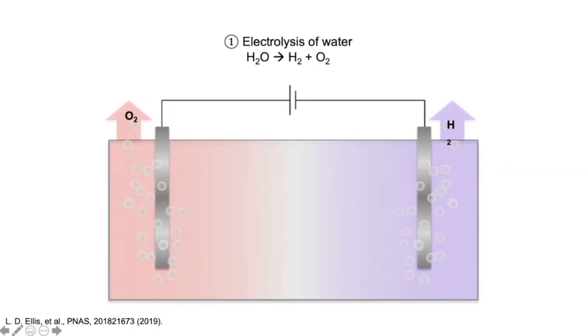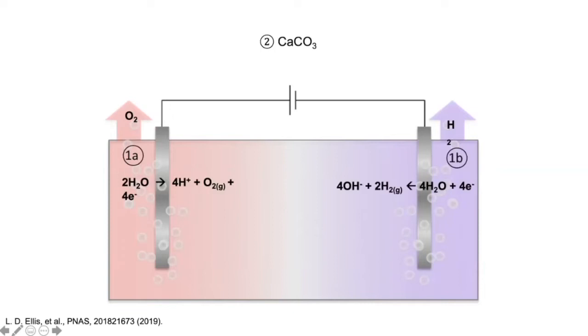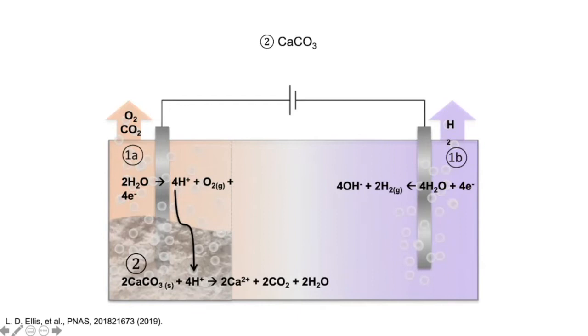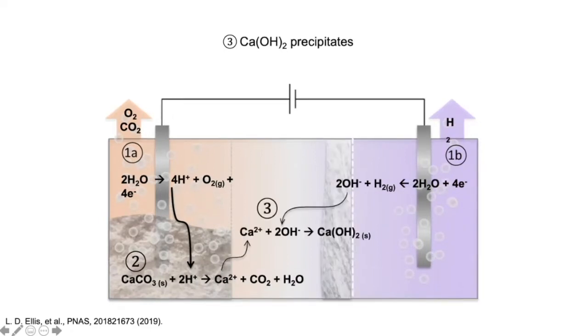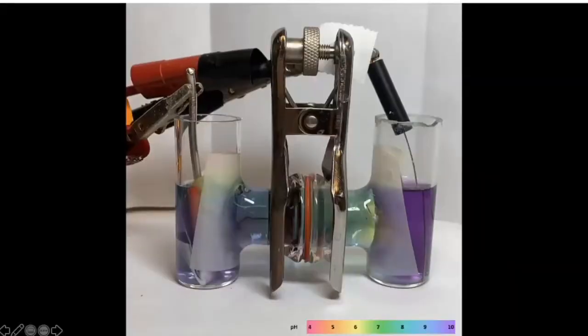Where does the electrolysis come in? Well, if we do what I showed you and produce an acid and a base in the electrolytic process, what we can then do is take our lime and dissolve it in the acid, which is on the left here, evolving CO2 along with the oxygen we produced at that electrode. And what this gives you is clean, pure CO2, which then can be sequestered or used for more valuable functions than just being sequestered. The chemical process that you can carry out if you simultaneously have the base present is to take that calcium that's now dissolved and at pH 10 or 12 or so, we precipitate out calcium hydroxide. Okay? And so this calcium hydroxide can now be captured.